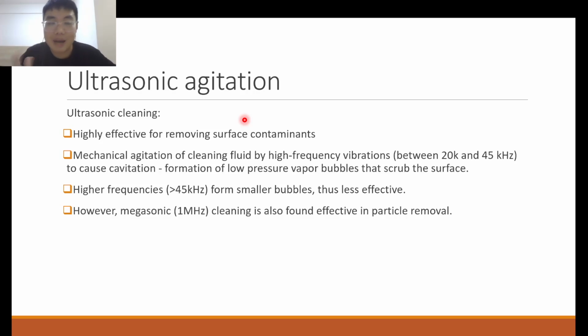And what actually is happening in the ultrasonic bath is that ultrasonic sound waves are being passed through the water, and this creates bubbles in the water that form and then collapse, and so this creates a rubbing action, an abrasive action on the surface of your material. So your spectacle glass, it removes all your dust, all your dirt, all your oil that's on your spectacle lens, through this action they call cavitation, the forming and collapsing of the bubbles in the water. Same thing here. We can use ultrasonic agitation by using high frequency vibration, like sound wave vibrations. Normally they use 20k to 45k hertz, kilohertz, to cause this cavitation of the bubbles that is able to scrub, to agitate, to remove any particles that are on the surface.